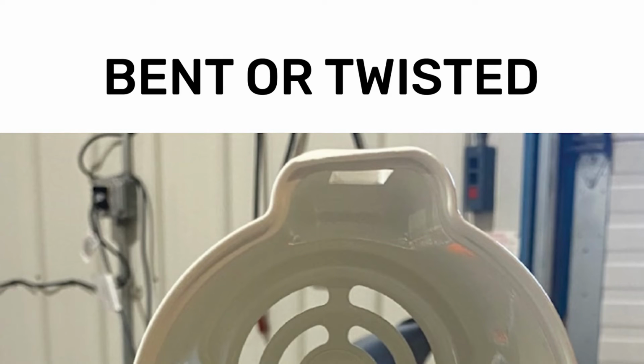For bent castings or misruns, like I mentioned earlier, bending or twisting might mean you don't have enough draft on your casting, so it can't easily eject out of the mold. In permanent mold casting, the exact amount of draft you need really depends on the wall height, but as a general rule of thumb, we'll say about 3 degrees.